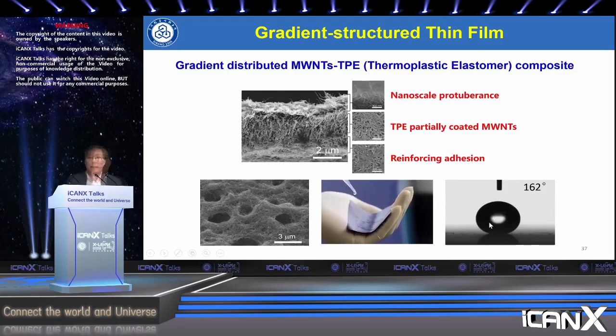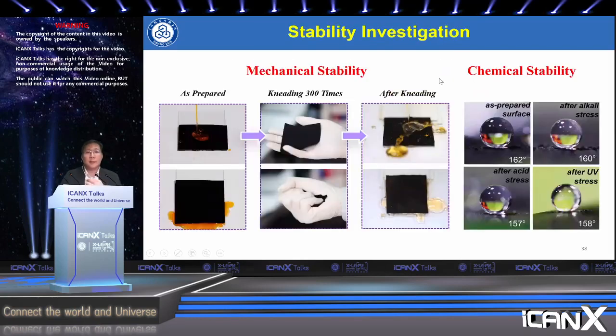And the contact angle of this water drop is larger than 150 degrees, so it has super hydrophobic properties. And this structure is also very stable. You can see here that we tested its mechanical stability and also its chemical stability. After kneading 300 times, when these films were combined with cotton, it still has very good hydrophobicity. And also we etched with alkaline, acid and UV, and you can see that the contact angle is still larger than 150 degrees, which shows the very good chemical stability.